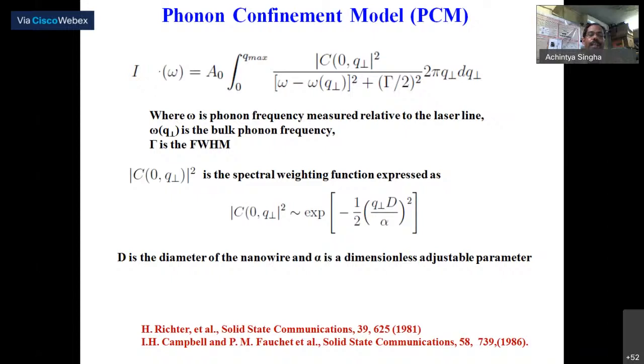From this model you can calculate the intensity of the Raman mode, which is given by this top equation, where omega is the frequency, omega q represents the phonon dispersion curve, and the function with zero q represents the weighting function, which is a function of the diameter or size of the particle. So from this intensity you can see that the Raman mode intensity is a function of the diameter, and that will also change the shape. From this model you can estimate the particle size from the Raman spectrum. So go next.